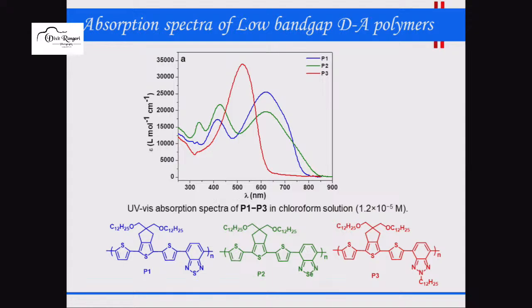So you can see this red color graph. There is only one peak in the absorption. Yeah? That means it's only coming from the conjugation, and there is very little contribution from the donor acceptor charge transfer band. But in the second and third cases, where you have the thiodiazole and selenodiazole, you have 2 bands. That means the second band, which is the higher wavelength band, is coming from the charge transfer nature of this molecule. So when we excite this molecule, there is a transfer of charge from donor to acceptor.